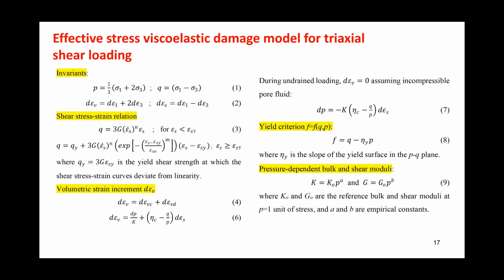So before yielding, we have elastic behavior. After yielding, when we reach Q_y, then the damage occurs. In this case now, damage is a function of the shear strain, epsilon_s. Now we need to formulate as well the volumetric change. The volumetric change is composed of 2 parts: the compression or consolidation volumetric strain and the dilation.